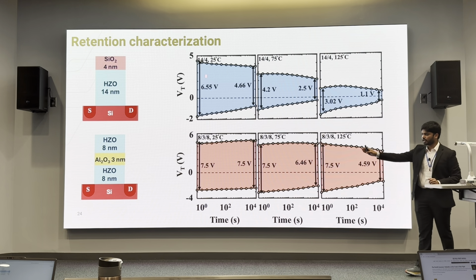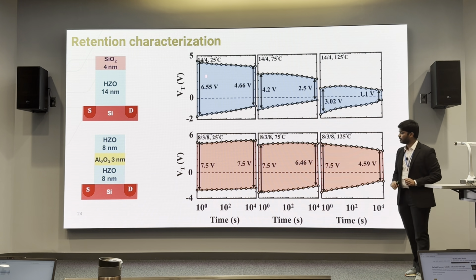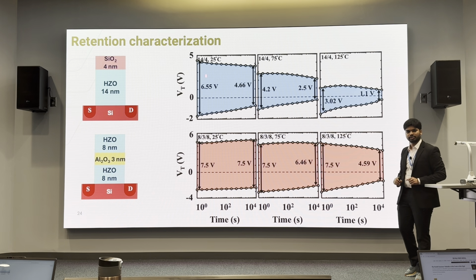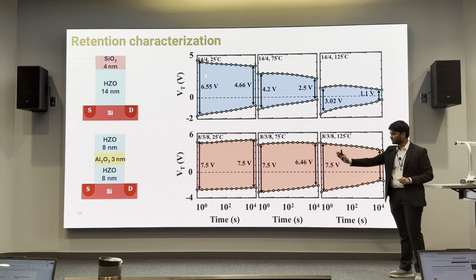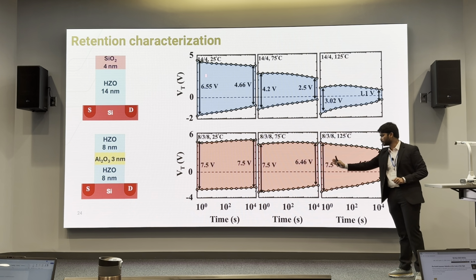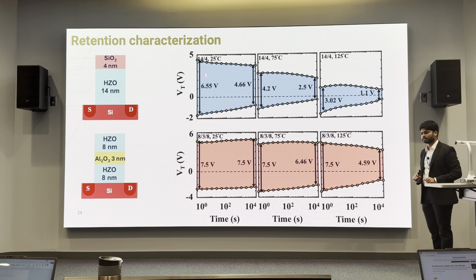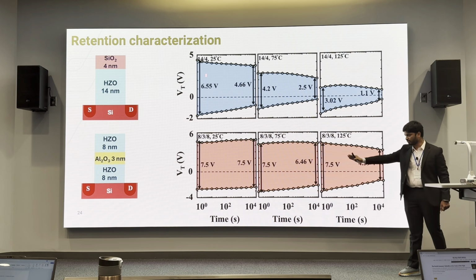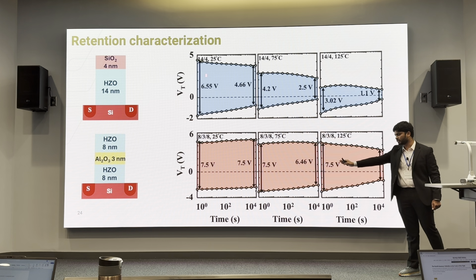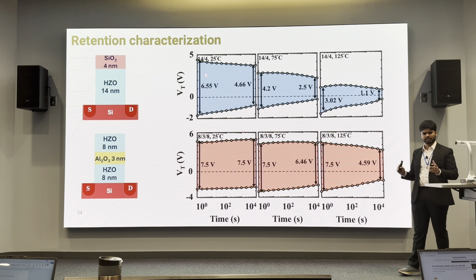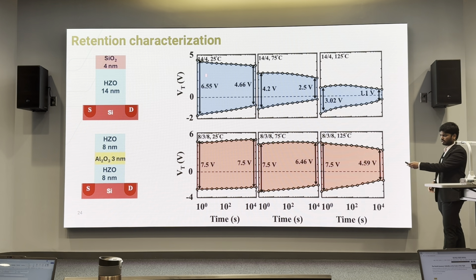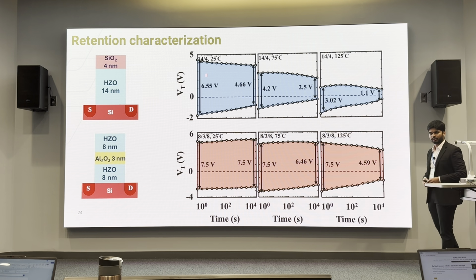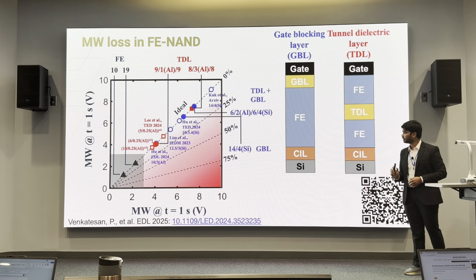Now what happens when we have a dielectric insert in the middle? When we have the aluminum oxide dielectric insert in the middle, we see immediately that the 7.5 volt enhanced memory window is constant at all the temperatures. And also at room temperature, we see that the 7.5 volts stays for the 10,000 seconds, which is about 3 hours. We do see increasing degradation in memory window at higher temperatures though.